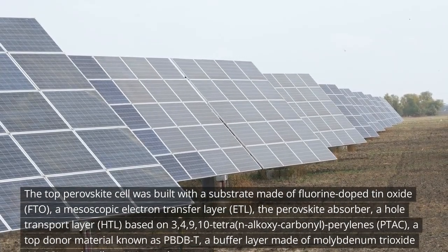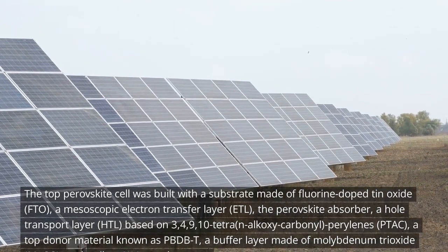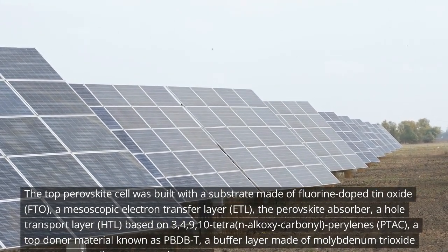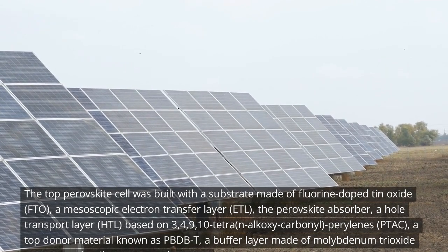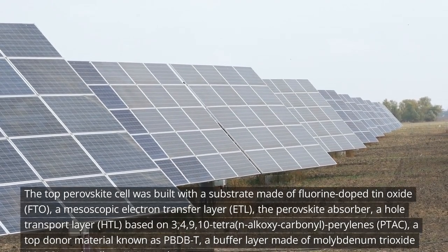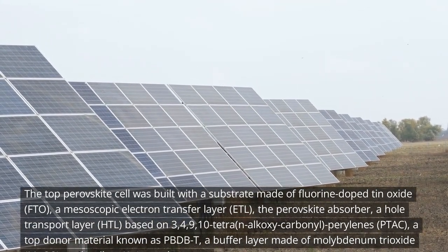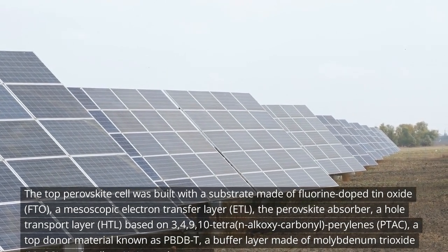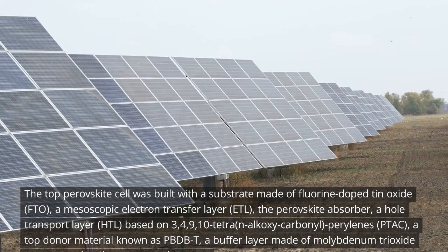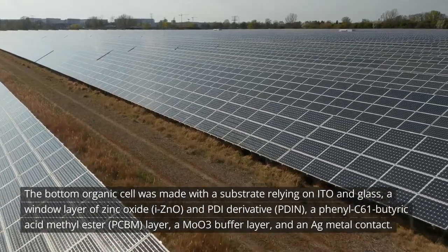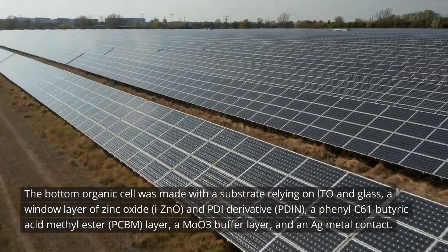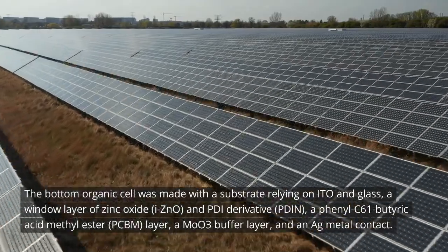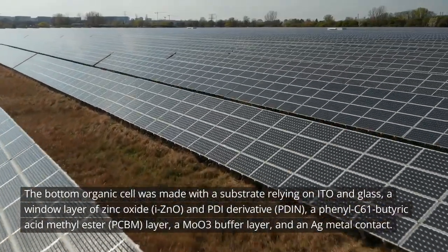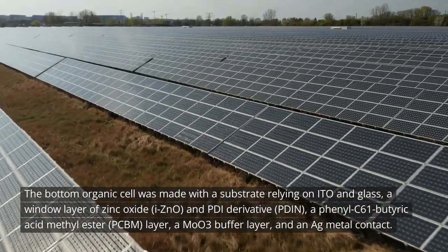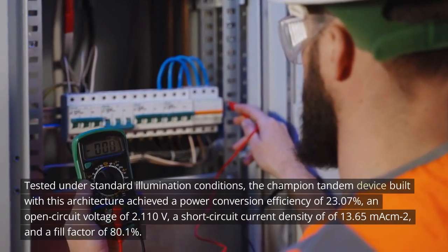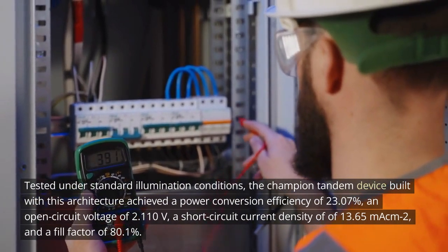The top perovskite cell was built with a substrate made of fluorine-doped tin oxide, FTO, a mesoscopic electron transfer layer, ETL, the perovskite absorber, a hole transport layer, HTL, based on 3,4,9,10 tetra-N-alkoxycarbonyl perylenes, PTAC, a top donor material known as PBDB-T, a buffer layer made of molybdenum trioxide, MoO3, and a silver, Ag, metal contact. The bottom organic cell was made with a substrate relying on ITO and glass, a window layer of zinc oxide, ZnO, and PDI derivative, PDIN, a phenyl-C61-butyric acid methyl ester, PCBM, layer, a MoO3 buffer layer, and an Ag metal contact.